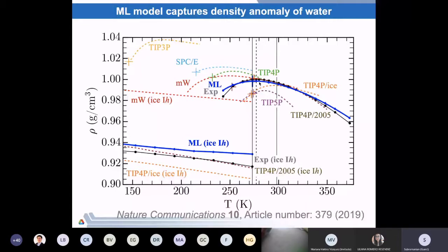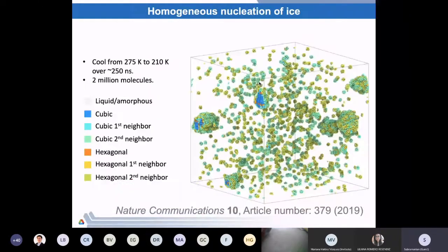The important aspect about this model is that it is a coarse-grained model. So the model is 2 to 6 orders of magnitude cheaper than the best available non-polarizable or polarizable model respectively. And what that means is that now you can use these efficient and accurate models to look at phenomena much beyond the homogeneous nucleation of ice.